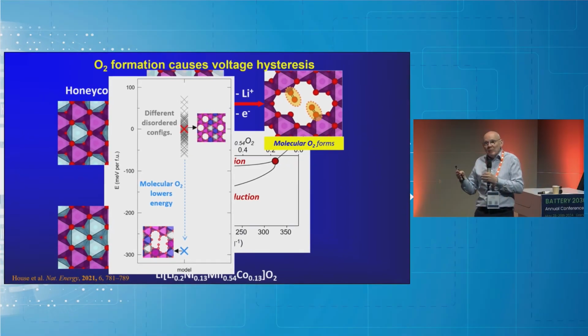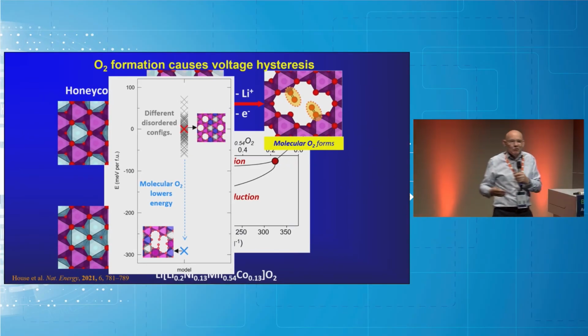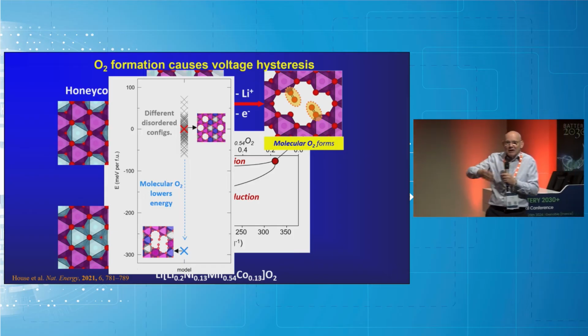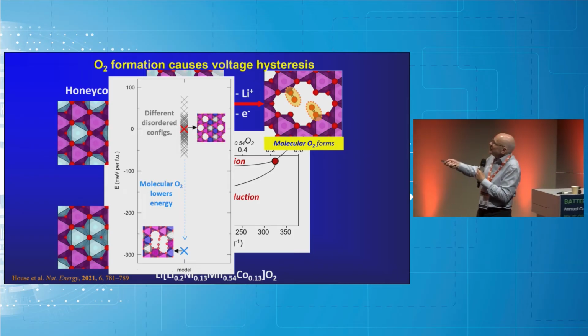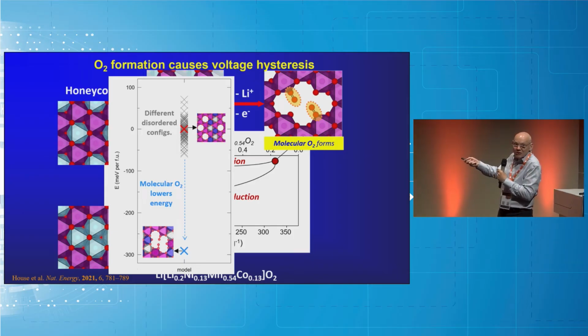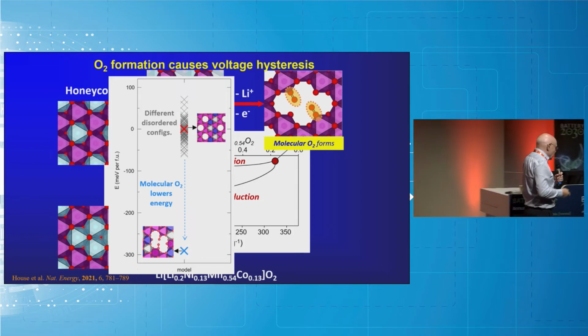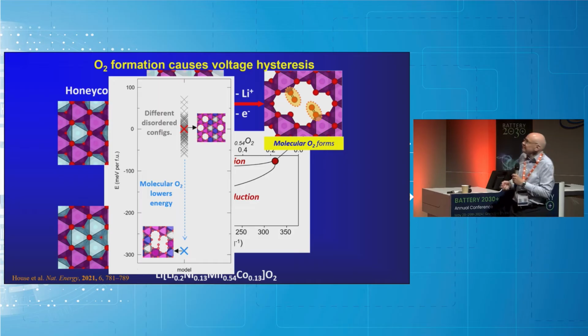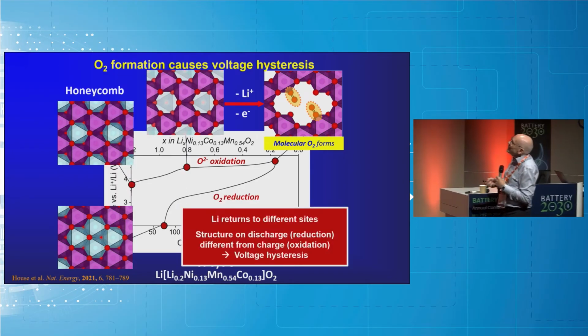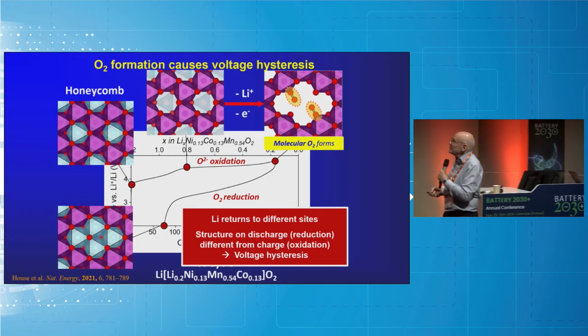But to have it happen, it's a bit like being allowed to cross the street. You've got to have the sign that says you can go. You have to have somewhere for those O2 molecules to go. And without those clusters, the O2 couldn't form, even though energetically it might want to. And as I said, lithium returns to a different set of sites, different energy, and again, we've done DFT on this structural transition as well as this one, and you do indeed get that 1 electron volt energy loss.